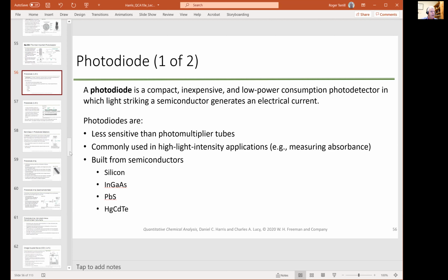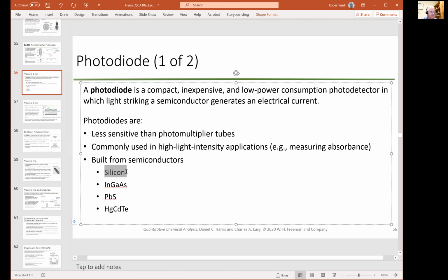And so I think the best way to think of a semiconductor is thinking of intrinsic, say, silicon, right? Now, silicon has a diamond structure, which means that the atoms in silicon are arranged tetrahedrally relative to one another. And because each silicon has 4 valence electrons, you can make a perfect crystal of silicon. And that perfect crystal will essentially insulate electric charge because there are no free electrons in it.